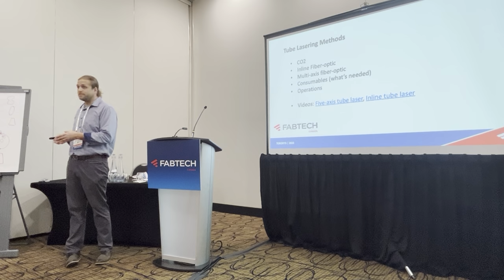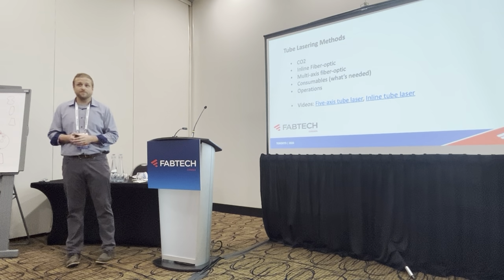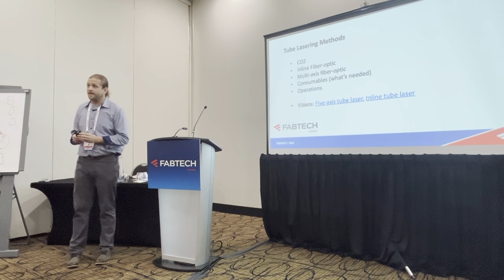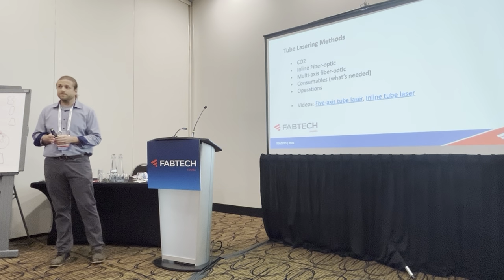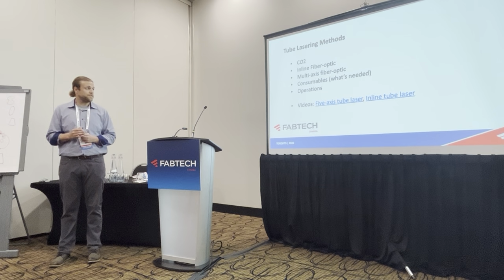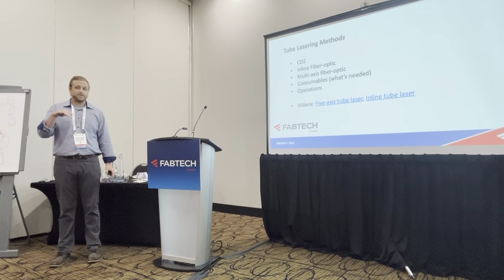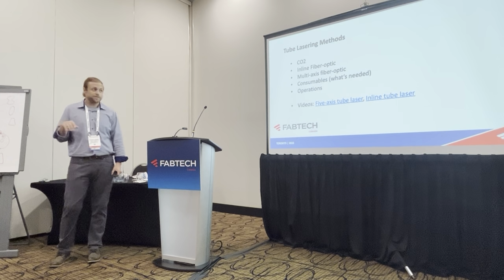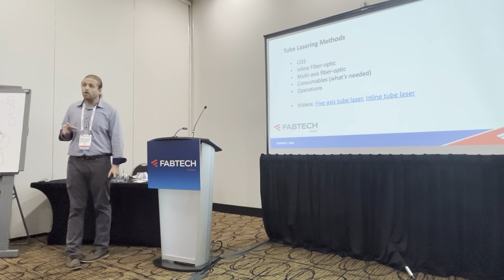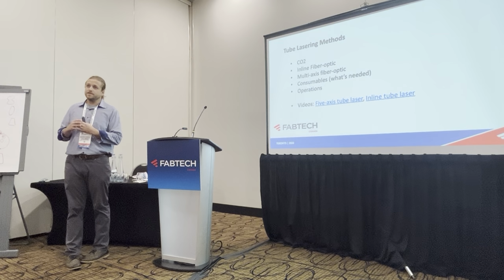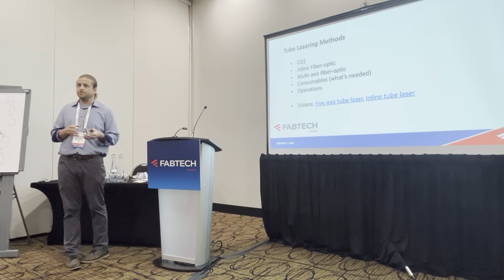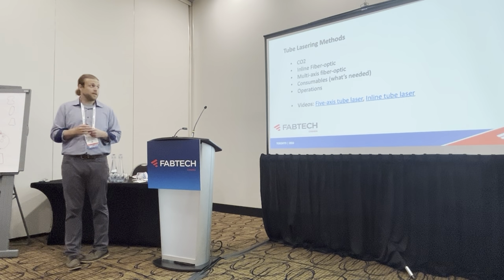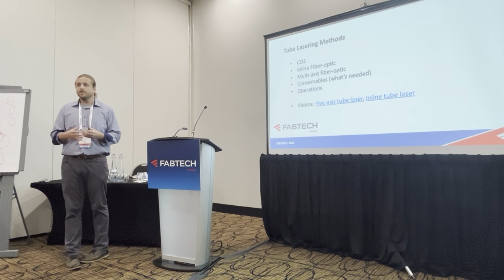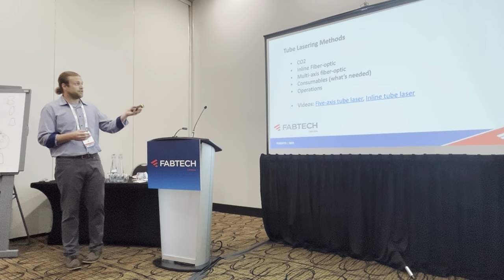CO2s to fiber lasers, speed is a huge difference. Fiber lasers are much faster on your thinner materials. A lot of times what you will see in that 4,000 to 6,000 watt laser range is right around .188 wall thickness, is where you'll see a lot of your operators will sometimes have to switch over to oxygen to account for material issues or whatever it is, because it starts to cut cleaner, but your speed reduces. You can cut much faster with nitrogen on your thinner materials.